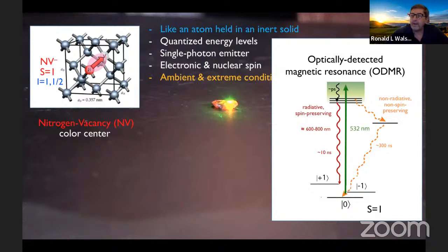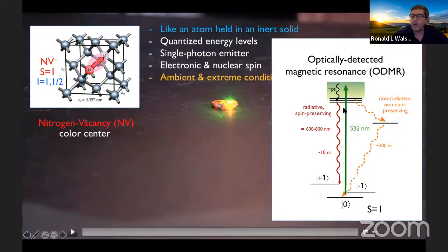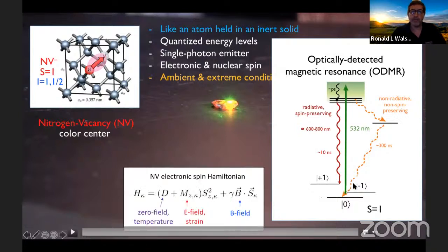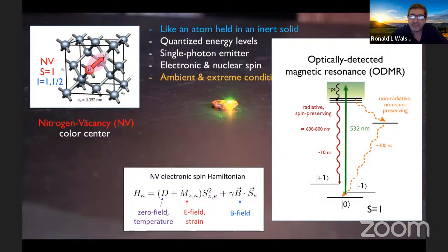So to repeat, 2 decay processes. And if you're in m=0, really only 1. You absorb green and you radiate back down to 0 without changing your spin state. You emit photons, red photons. Plus or minus 1 levels have about a 50% chance to return to where they started and emit a red fluorescence photon, or non-radiatively decay down to m=0 on a much longer time scale. So the difference in the decay pathways between the 0 and the plus and minus 1 levels leads to some very important consequences that I'll mention in a second.